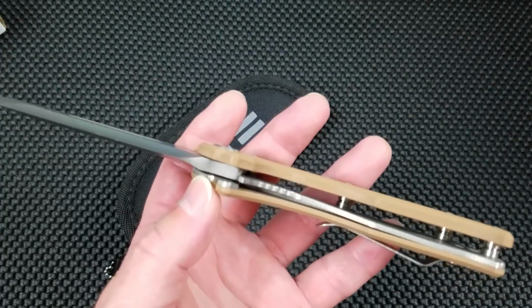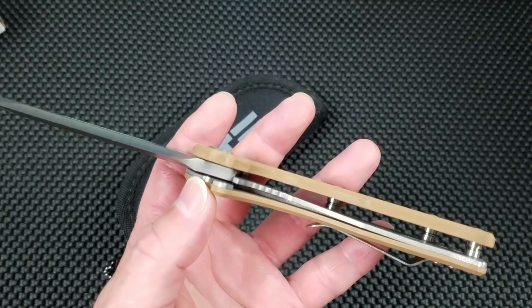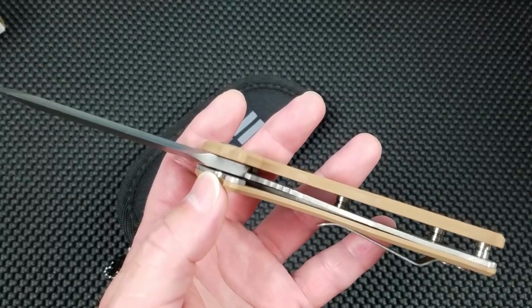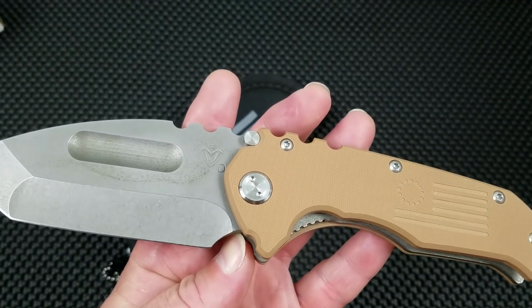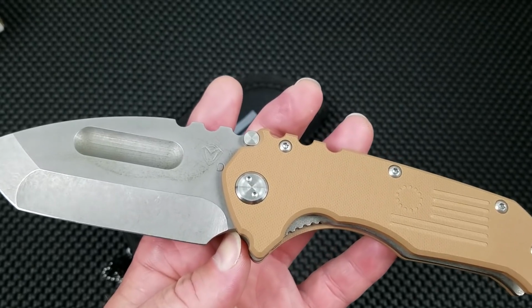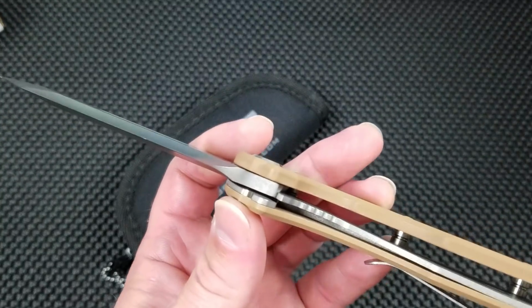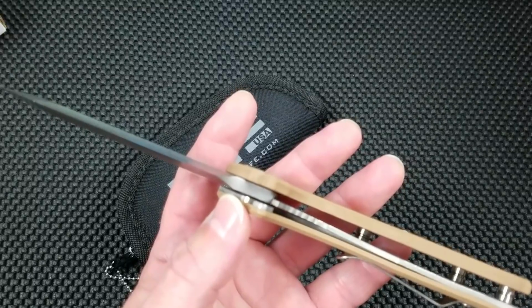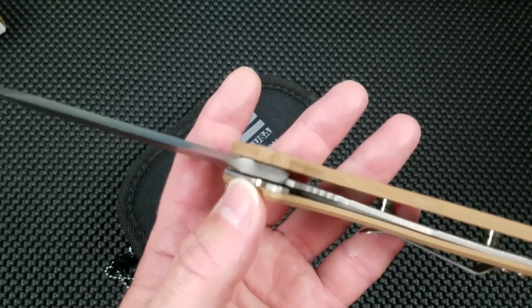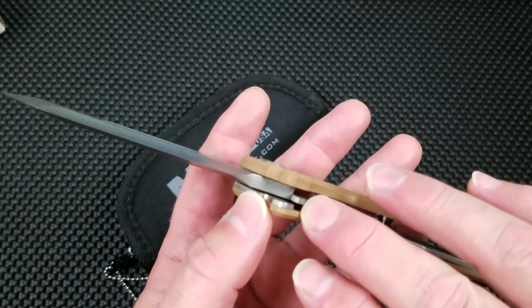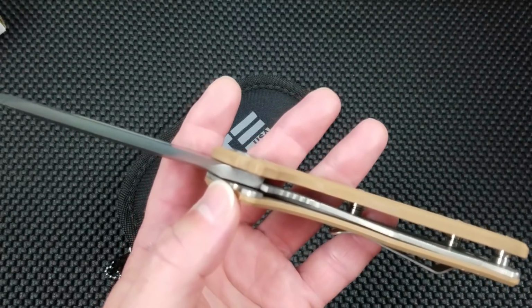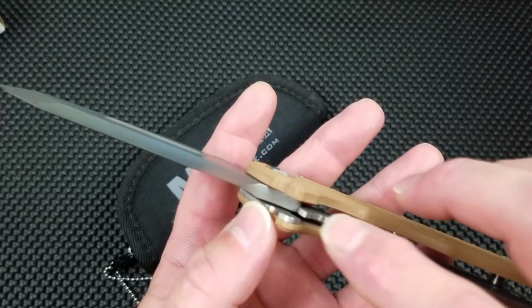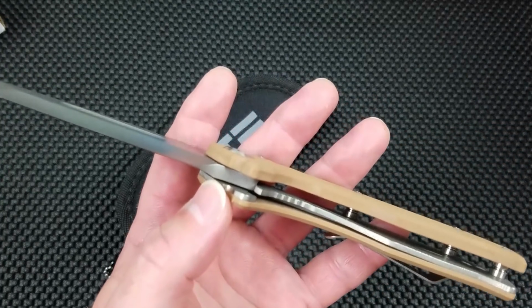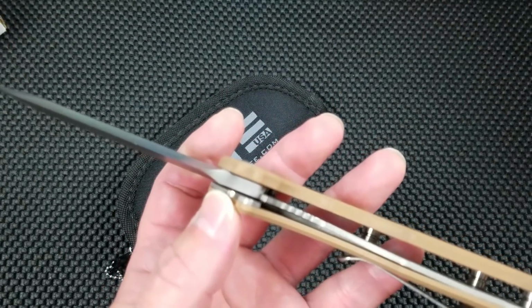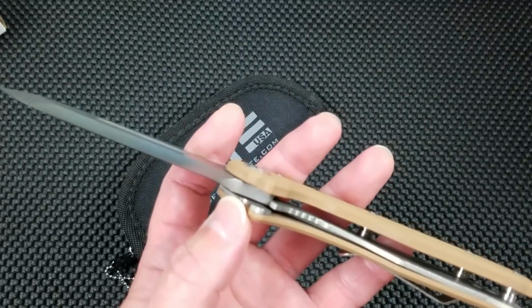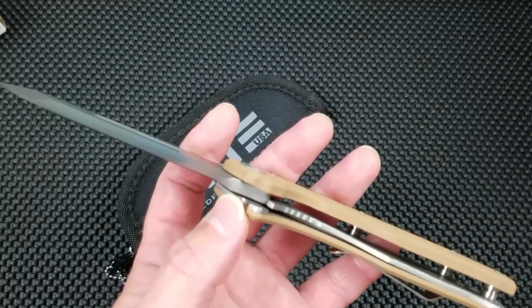It cannot be. Even the beta titanium that Mission Knives uses, you can't Rockwell it any higher than like in the upper 40s, guys. And D2 typically is going to be 60 to 62 Rockwell. You're looking at 20 points difference between those two materials. So you know, I mean, just common sense is going to tell you there's going to be wear issues. Now, just the common wear can be sort of eased by carbidizing the lock face, and that's basically you microscopically weld carbides onto the surface of that lock, and that's great. It stops that wear issue, and it stops the lock stickiness that you can get between a hardened material and a softer material. But what you cannot mitigate is impact deformation.